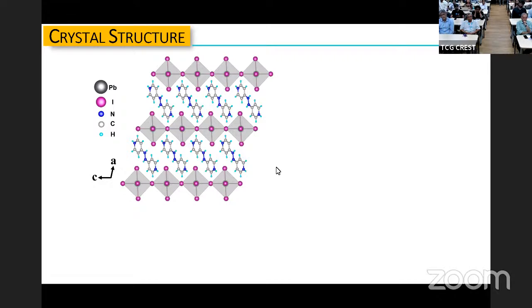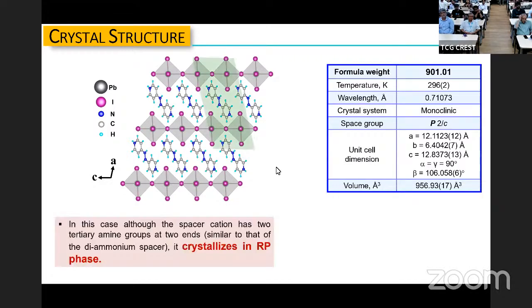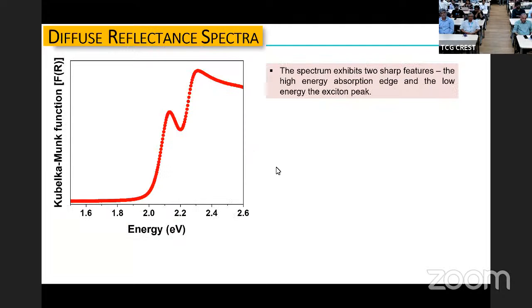But that plays a very important role in determining the properties of this. I'll show you later that it is essentially because this iodine wants to have hydrogen bonding with that one and with that one. That's the reason this molecule tries to go in a tilted manner, staggering the two interlayers. By doing that, the layers come closer together, and that leads to an interesting decrease of the band gap and plays a very important role. And this head forces itself into the inorganic layer to maximize the hydrogen bonding. That's the crystal structure. We don't have to spend more time on that.